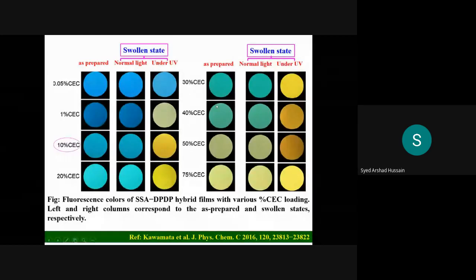Then what we did, we exposed this using normal light. In the second column, you see the as-prepared and normal light images are the same. But when we exposed this film under UV, just using a UV torch, and recorded the image using the same mobile camera, you can see in the last column that a color change occurred. The color change was most prominent at 10% of CEC. You see it's blue, then under normal light again blue, but under UV you see a deep or dark yellow.